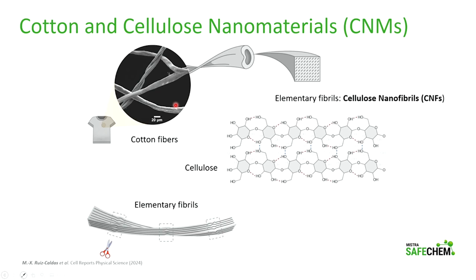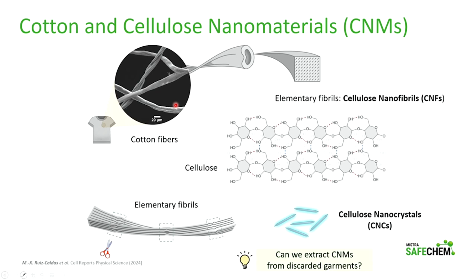Now, if we take these elementary fibrils and through a chemical process we manage to cut them in certain locations, then we can isolate rod-type nanoparticles, cellulose nanocrystals. And my work during these last 4 years has been to extract these nanofibrils and nanocrystals from cotton. These 2 are called in general cellulose nanomaterials, and the purpose is to see if we can, instead of using virgin sources, use discarded textiles as a source of cellulose nanomaterials, or CNMs.